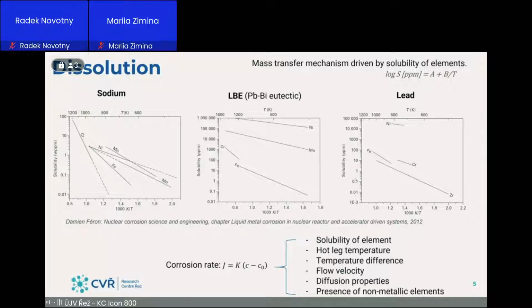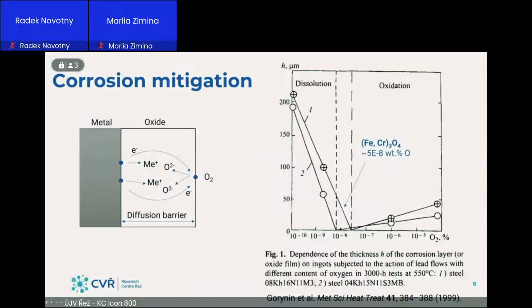So the corrosion rate depends on solubility of the element, the difference between hot leg and cold leg, and flow velocity, and also there is the very important presence of non-metallic elements that can speed up or slow down the corrosion process. So what we can do with this corrosion, the simplest idea is to grow a diffusion barrier, that is oxide, and slow down this dissolution process.